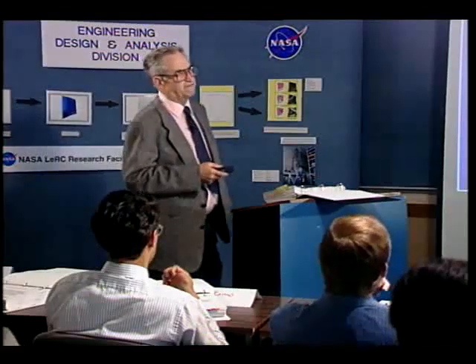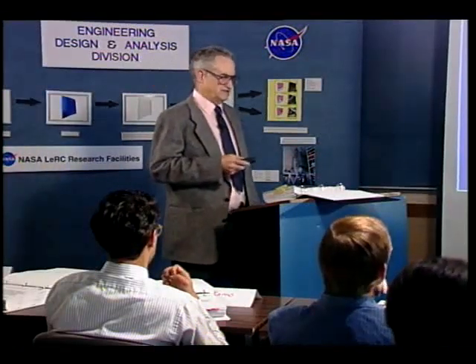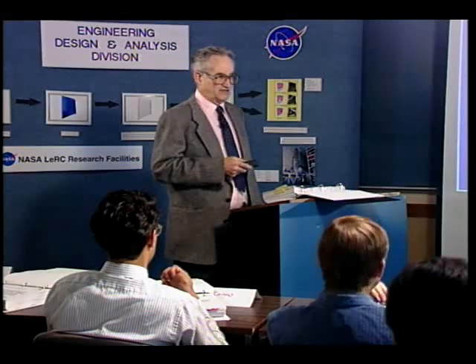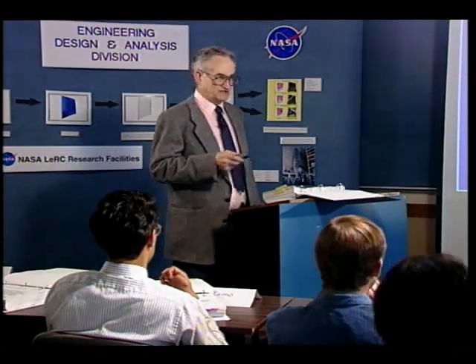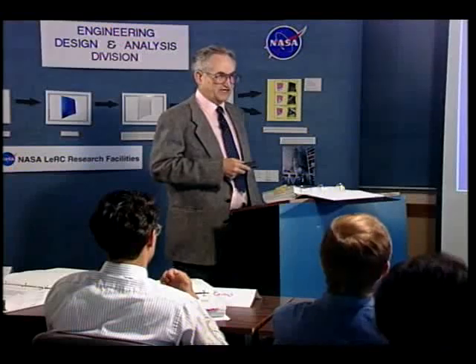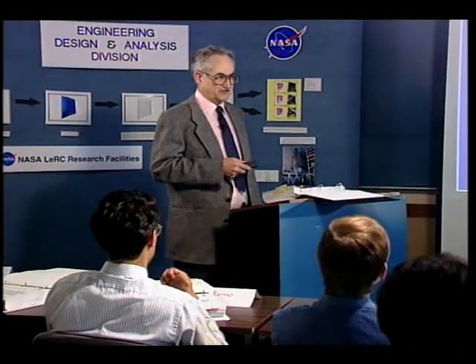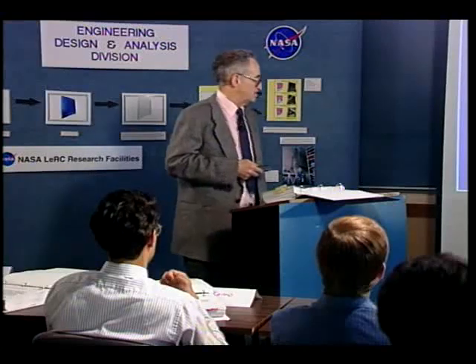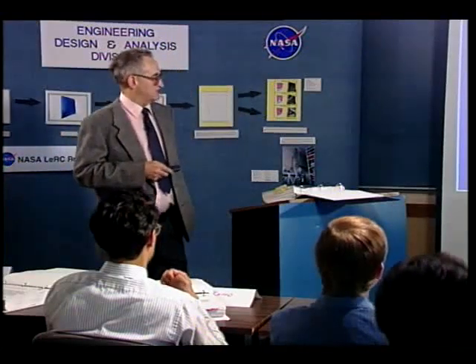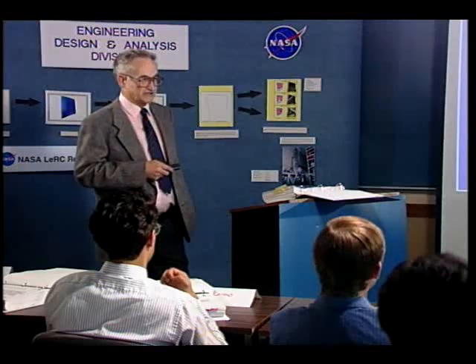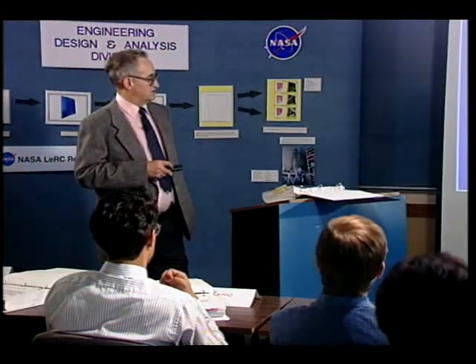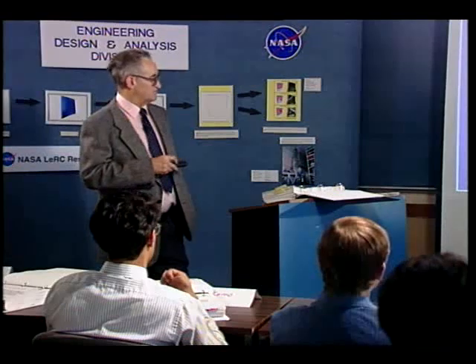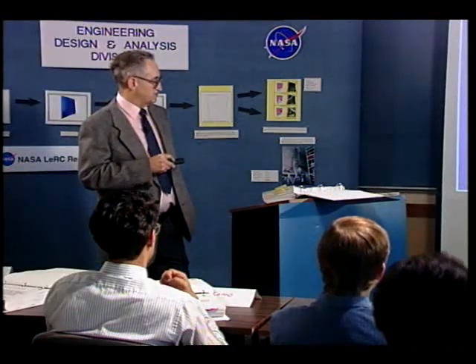Whenever you do an electroplating process, it's done in some sort of an aqueous environment. So, as you know from charging your battery, you get free hydrogen whenever you put electrodes in water. So you have free hydrogen ions, and of course hydrogen can go where anything else can't go. So you get hydrogen given off during the process, so unless you bake the material right after it, you're in trouble. Now, cadmium melts at 610 degrees, so its service temperature is limited to 450.